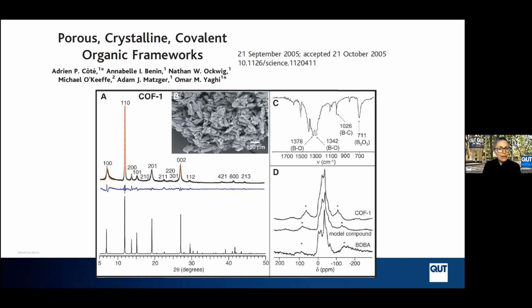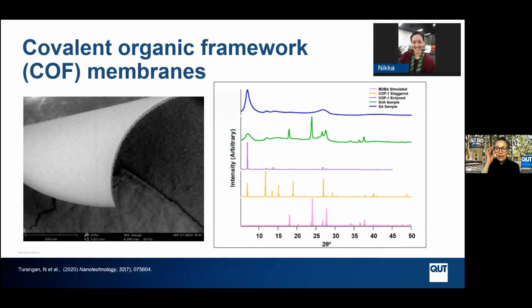doing things like storing gases or sieving gases if we want to do some sort of filtration of gases, this sort of thing. So COFs are generally synthesized into this crystalline form, something like a powder that you can see here in the SEM image. They are highly crystalline. The XRD shows you that. And typically we can confirm the presence of those boroxine rings that are formed after the condensation reaction through the use of infrared spectroscopy.